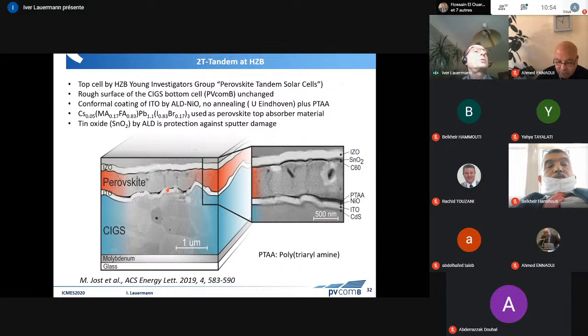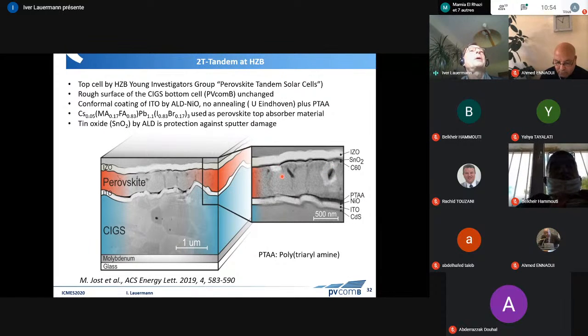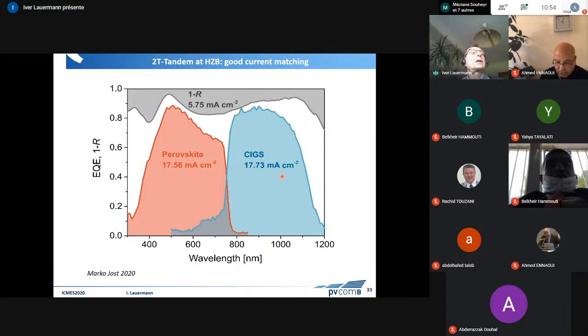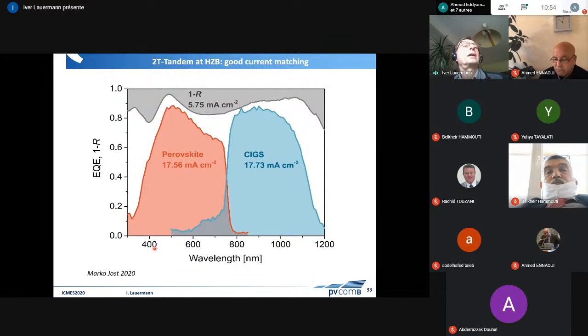Now we work with nickel oxide, and the first very nice efficiency was achieved just a year ago, or almost 2 years ago, in collaboration with the group of Maria Adriana Creatore in Eindhoven. They provided the nickel oxide, which was used in the recombination junction. This is what it looks like: CIGS, recombination junction, fairly complicated composition, and then on top, the perovskite. And this is when you look at the current matching. This is the part of the current from the solar cell that comes from the perovskite, from the high energy light. This is the part from the bottom cell, the CIGS, and they have to be as close as possible in order to reach current matching.